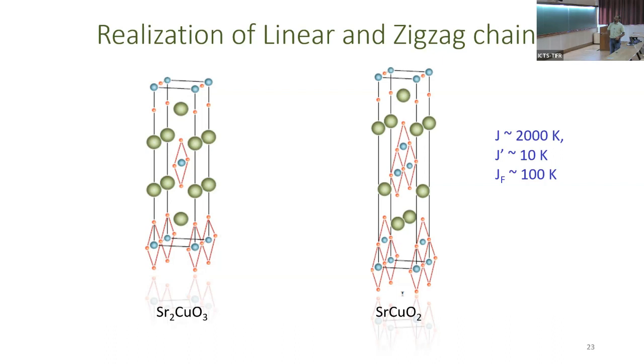So this is a linear chain. Here, blue balls are the copper atoms, which are carrying a spin half, and they interact with each other via this intervening red ball, which is the oxygen atom. So this is the copper-oxygen-copper superexchange path. Along this direction, there's no intervening anion, so there's no coupling between these two spins along this direction. And along this direction, there is a path actually, but it's rather too long. So the interactions are predominantly along the chain direction. And here the chains are zigzag. Otherwise, the structures are analogous.